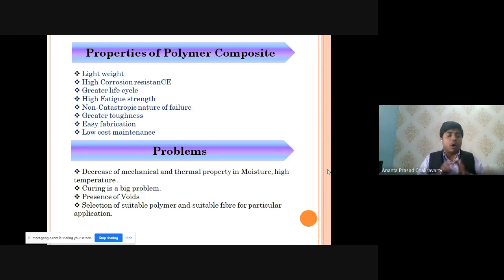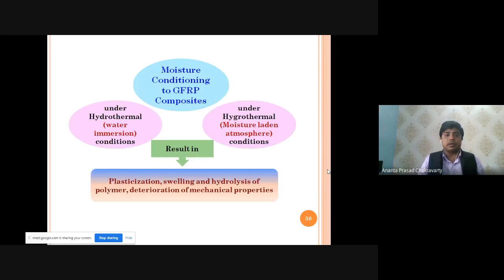We cannot achieve ultimate or optimum curing for that polymer, so that material cannot be hardened up to our desired extent. Presence of voids and selection of suitable polymers or suitable fibers for different classes of materials. Keeping this in mind, I have fabricated these materials and exposed them to a humid atmosphere, that is water immersion, and an environment where moisture is there with high temperatures.